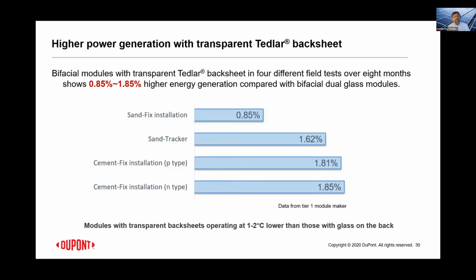The initial indications show that this is because the modules with transparent backsheets probably operate at a slightly lower temperature, anywhere from 1 to 2 degrees Celsius lower than those with glass on the back. And this is probably contributing towards the increased energy generation in this case. So this should be a good performance differentiator, we believe.